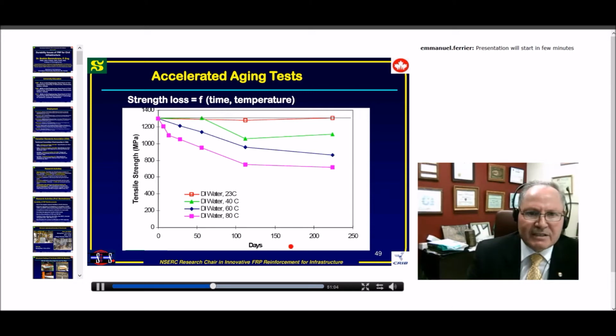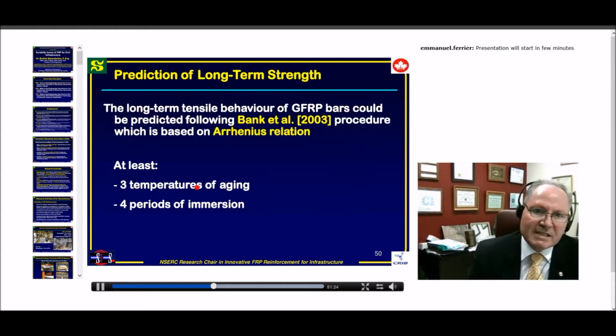This is about the days in conditioning, and we have different temperatures: 80, 60, 40, and 23. And as you can see, as we are increasing the temperature, the strength retention is reduced. And from this we can derive long-term strength. So to derive long-term strength, of course, this is based on the Arrhenius relation, as I said before.